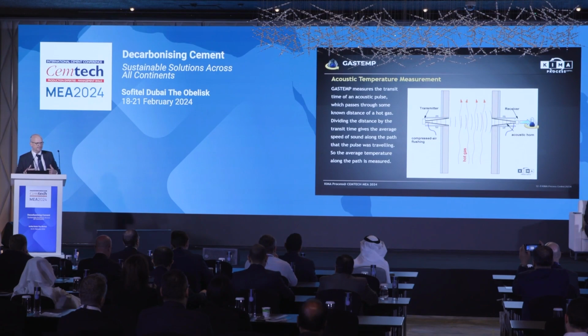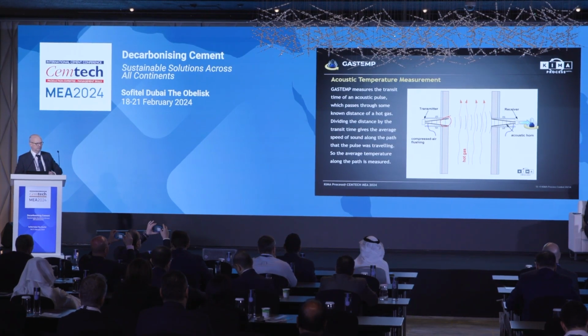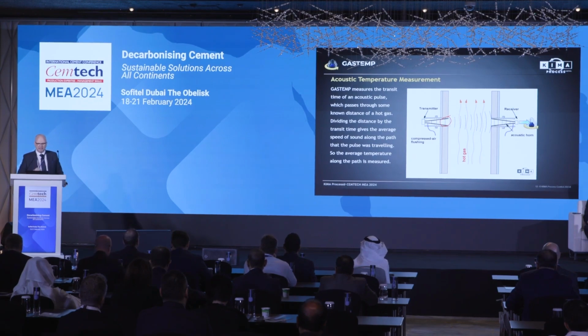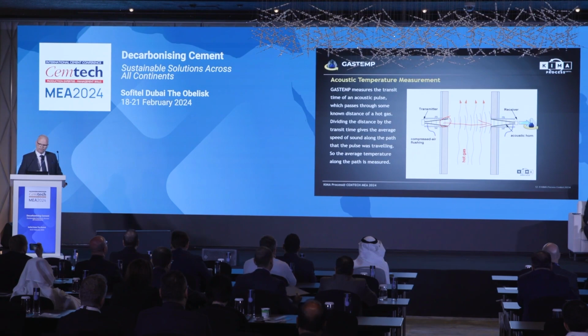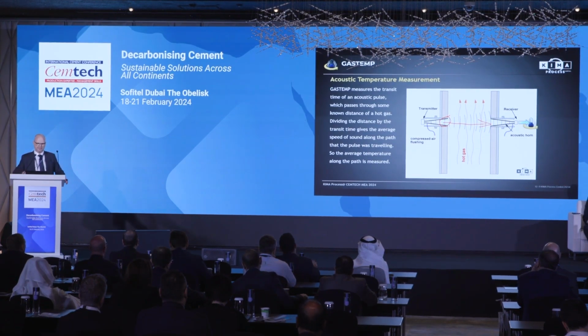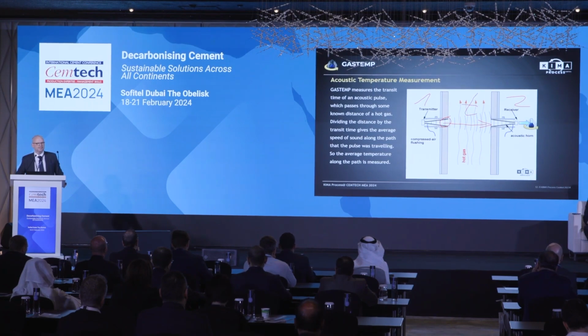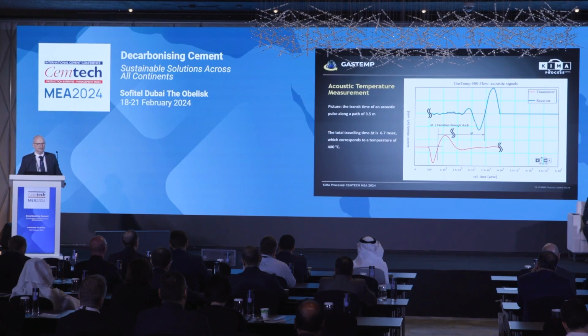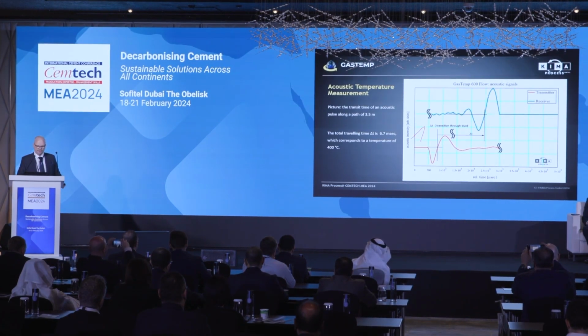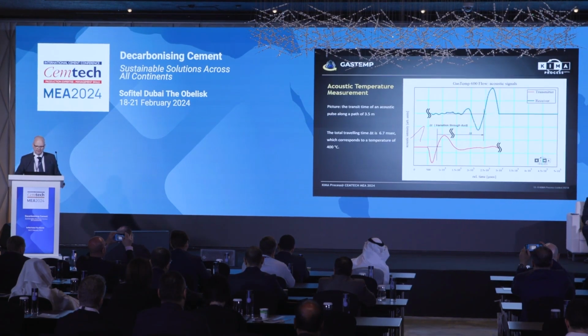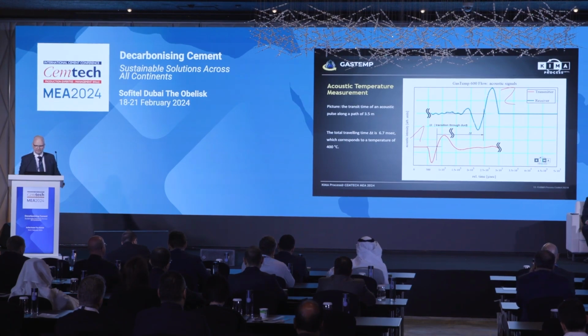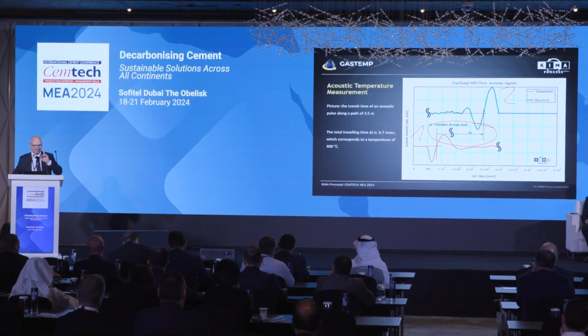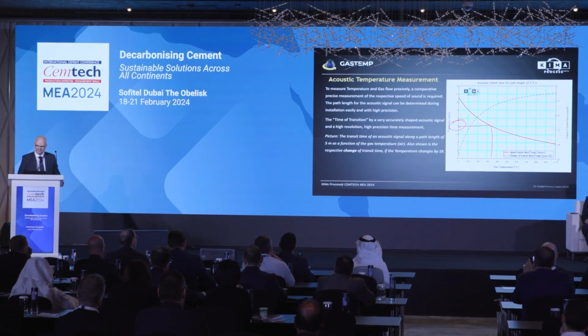We are working with so-called horns and transmitters, so we send an acoustic sound produced by a compressed air flush, similar to an air shock cannon. And we send this sound through the entire duct, the full cross-section. We have a microphone here and a microphone here. And the time this sound needs is 100% related to the temperature. We see here the first signal, that is the first microphone, and the second microphone on the opposite side of the duct. And this delta T, which we measure, is time, not temperature. This time we can now translate into temperature.